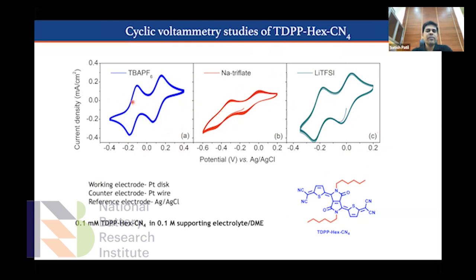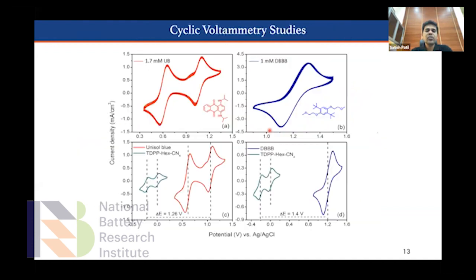So we could do very good reversible cycling. We did a large number of multiple cycles using TBAPF6, and indeed we found this material is very, very stable. However, when you go for sodium triflate and lithium TFSI, particularly sodium triflate, we did not find a very stable electrochemical potential in this class of material. So we stick with TBAPF6, and then this is all again cyclic voltammetry of a catholyte.